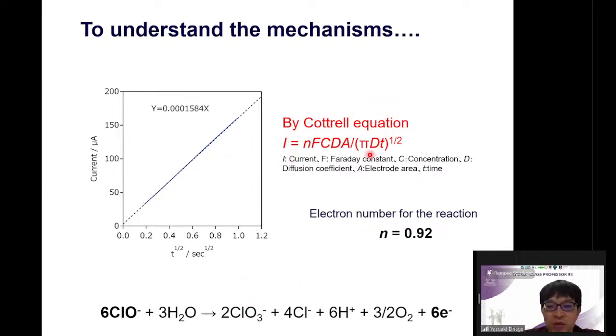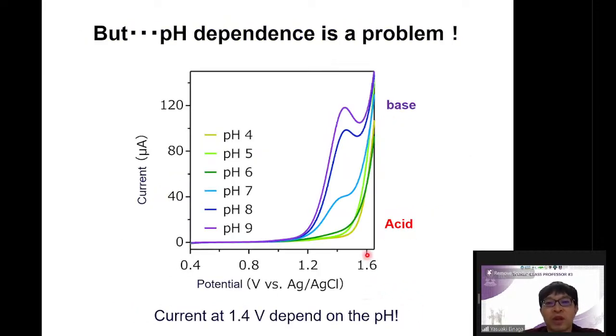By using this Cottrell plot, we could know the electron number for the reaction. By this Cottrell analysis, the oxidation reaction contains a 1 electron oxidation. So it means ClO minus is oxidized in this 1 electron reaction. So this is confirmed. And then we encountered a problem. What is the problem? This is pH, you know. In 2008, we reported the oxidation peak is very good, but this oxidation peak shows a pH dependence like this.